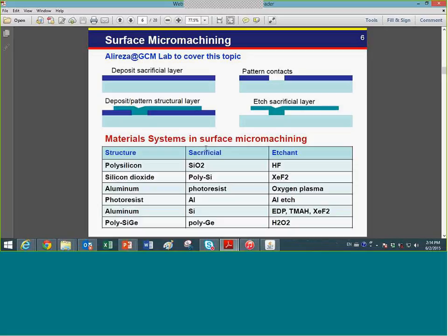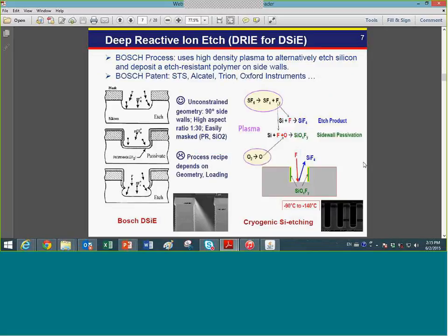In surface micromachining, the typical steps go from depositing a sacrificial layer, patterning the sacrificial layer, and depositing the structure layer, and then finally removing the sacrificial layer to release the structure. Depending on the application, you will need to select which material will be used as the structure material, such as polysilicon. This table gives you a typical example.